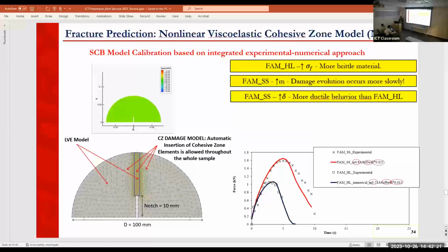So when we did the calibration, we created a finite element mesh mimicking exactly the same dimensions as the sample that you test in the lab. And then we play with those parameters, A, M, sigma F, and delta, until the results we obtain in the experiment match the simulation. This is what we call calibration. It's not a prediction, it's just a calibration. We try to match the curves.